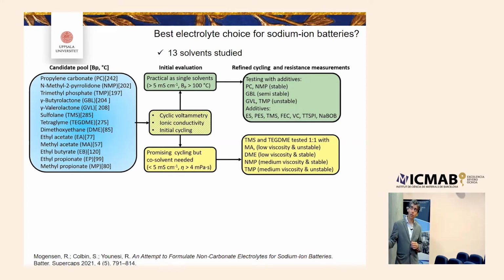We did an initial evaluation based on the conductivity of the electrolyte. Sodium PF6 was used in all these solvent mixtures. We did some initial cyclic voltammetry, ionic conductivity measurements, and initial galvanostatic cycling. Based on that, we decided where to go: either the solvent was promising, so we tried some additives to optimize the system, or we could see there was a need for a co-solvent because the conductivity was low or the viscosity was too high. So we took two different approaches to look at these electrolytes.